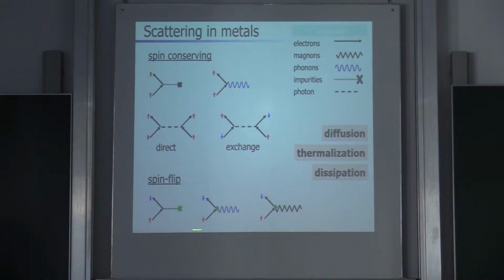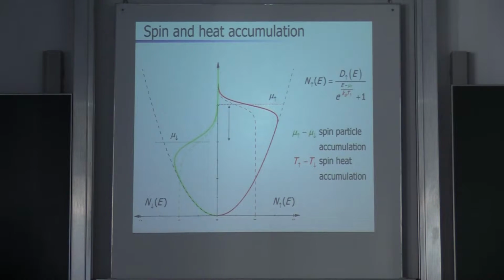Now the point is that these processes in most systems are weak. Spin-orbit interaction is usually a weak process. It's much smaller than all the other scatterings. And this you usually invoke in order to define the spin accumulation, right? You're exciting the system, driving some spins into the system, and we assume that they diffuse quickly. That means we can talk about a quasi-equilibrium state, and they are also exchanging energy with the environment quickly. So the electron temperatures and the phonon temperatures become the same very quickly as well.